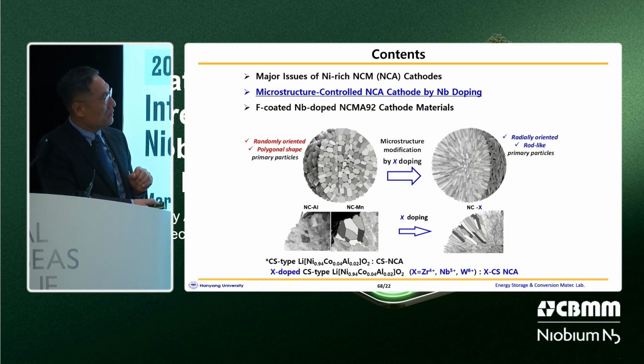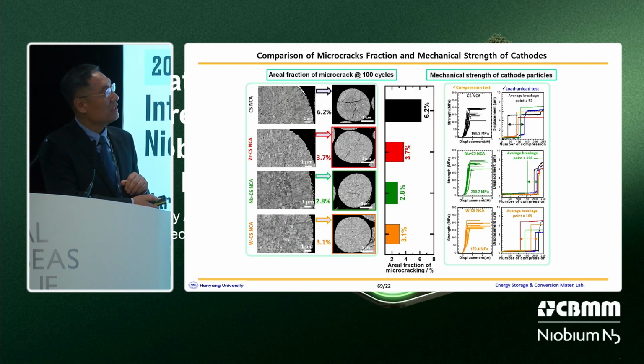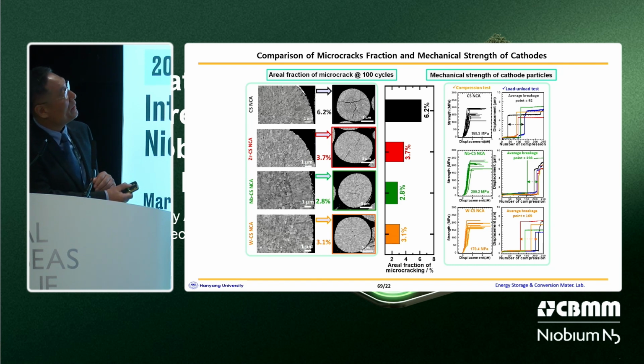Therefore, we prepared 4 different kinds of cathode materials. One is a CS-type NCA cathode with a nickel content of 94% as a baseline material, and then we doped it with zirconium, niobium, and tungsten, denoted as XCS NCA cathode materials. This is a comparison of microcrack formation and mechanical strength of the prepared cathodes.